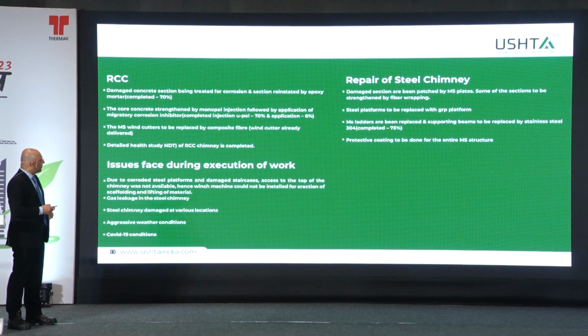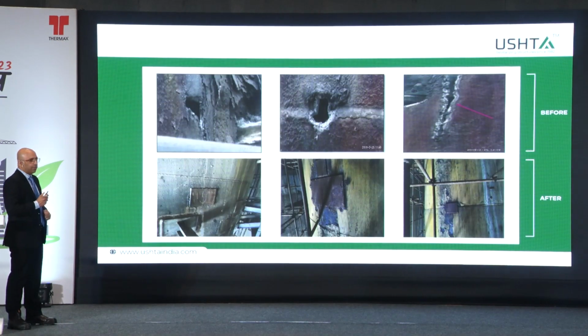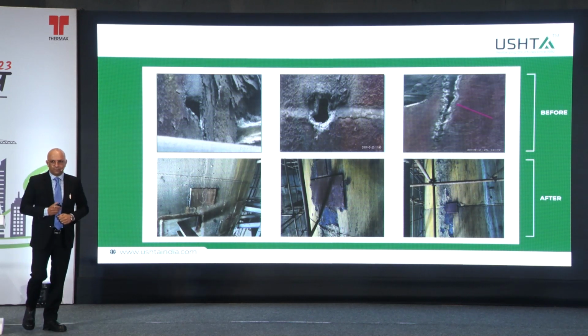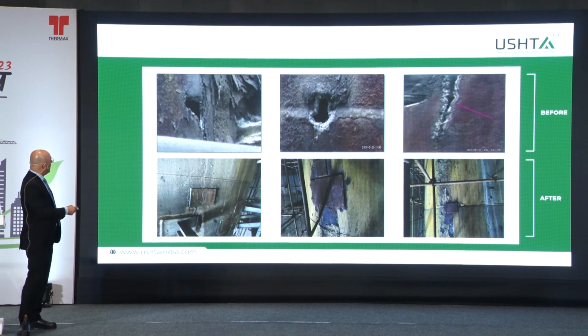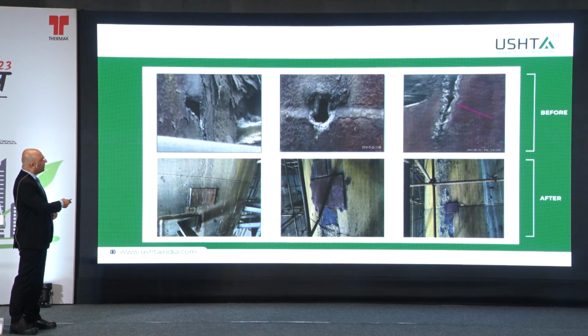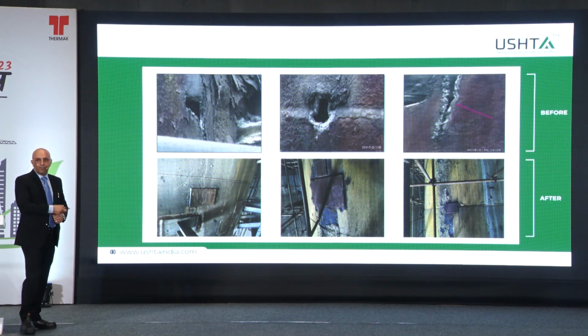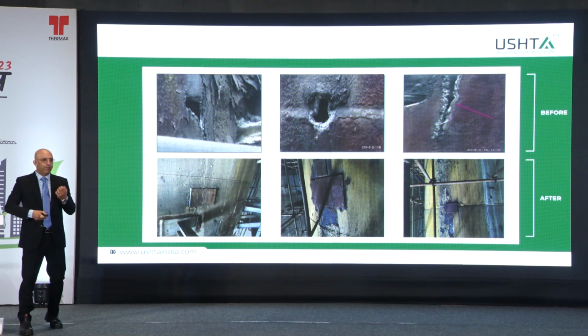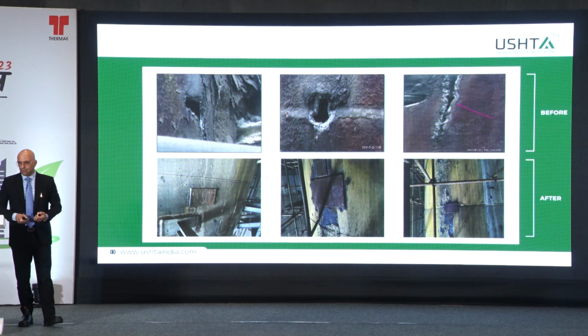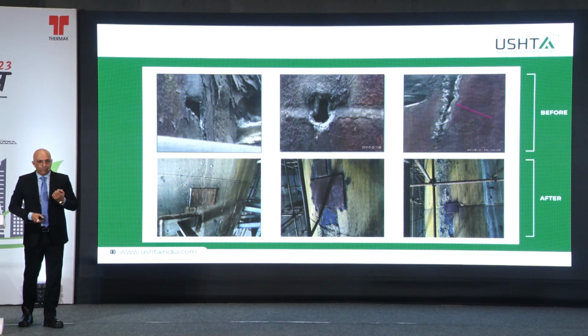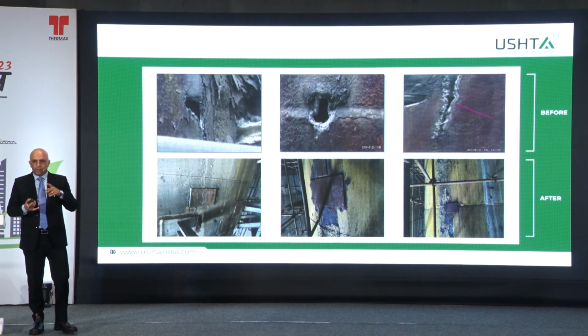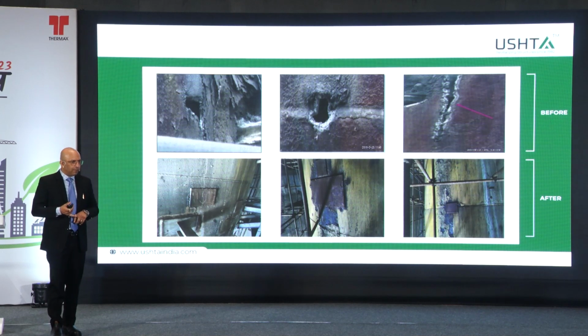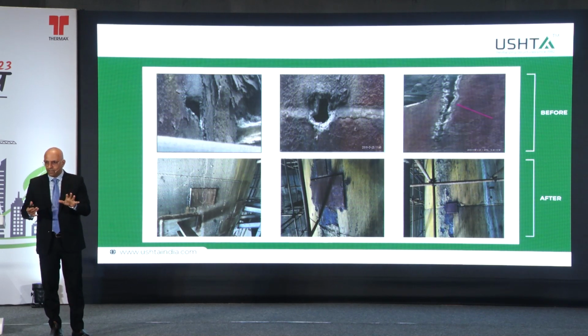Inside the structure you can see the condition of the steel stack. You can see the layers, almost 30-40 layers of steel here. At places where we tried to weld, it would crack because the thickness left was only 1 mm. Now we were left with no option. We can't add additional steel plates because while welding it was just tearing apart.